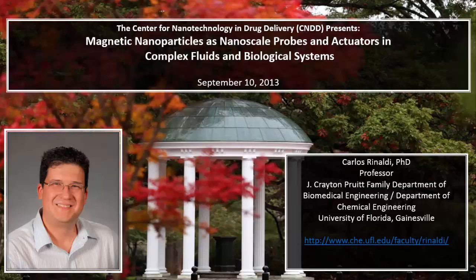So what we did is we took our cobalt ferrite particles, coated with polyethylene glycol, so they don't have specific interactions with the gelatin molecules. This is at 70 degrees C, where the gelatin is completely melted, and you can see that there's an out-of-phase peak. Its location is a bit above the frequency range of our instrument. If we lower the temperature, we see the peak decreases in frequency, and then at very low temperatures where the matrix is completely gelled, we don't get an out-of-phase peak signal.